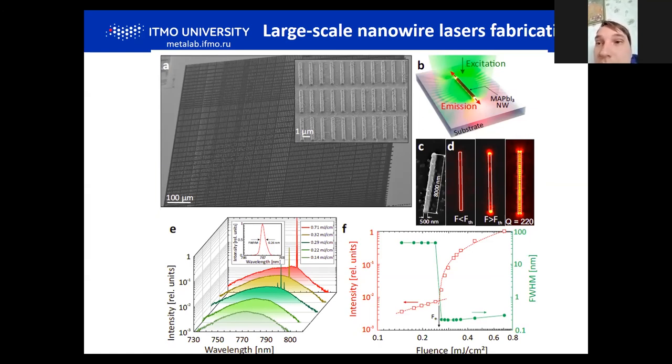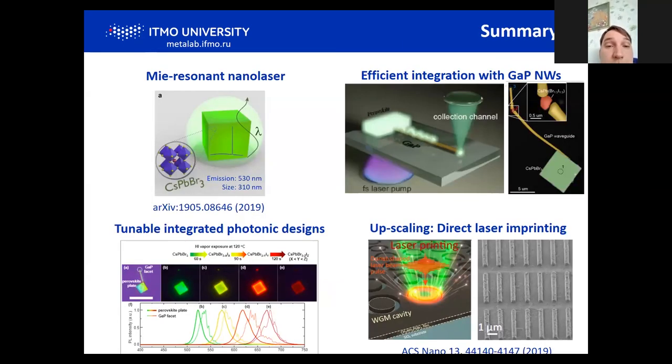More importantly, this upscaling technique can be applied for creation of sub-wavelength lasers. We demonstrate cutting by a rectangular laser beam to create nanowires with cross section less than the emitting wavelength — wavelength is around 800 nanometers, and the cross section is around 500 nanometers. The low thermal conductivity of perovskites helps preserve light emitting properties even after ablation — even after strong overheating, after cooling it again emits light well and provides lasing. This is the first demonstration of nano lasers made not chemically but by laser.